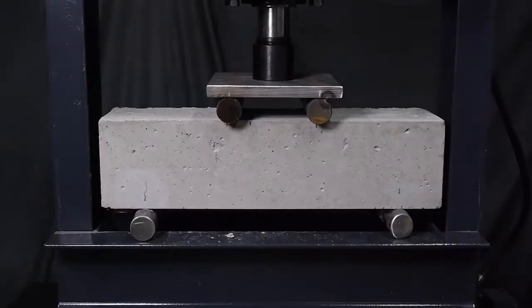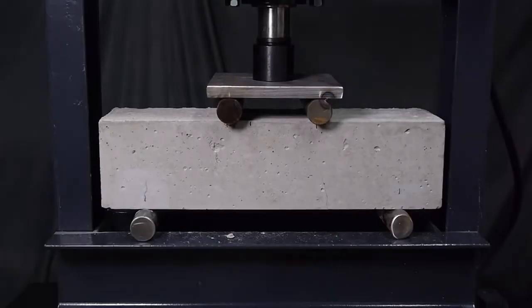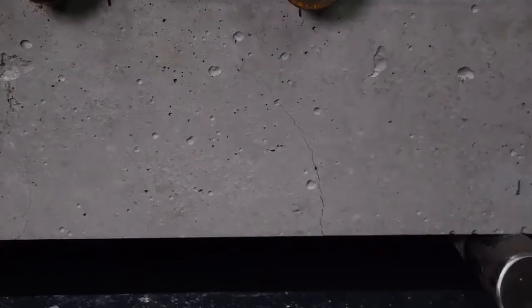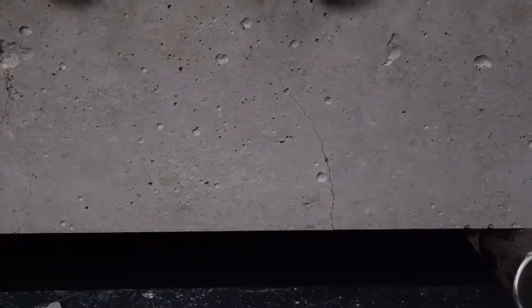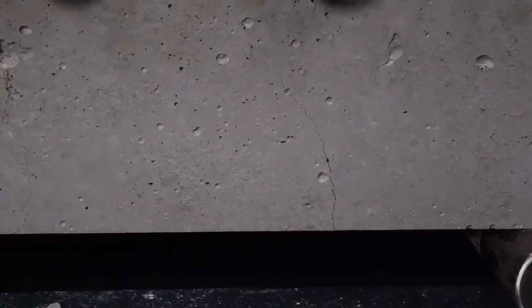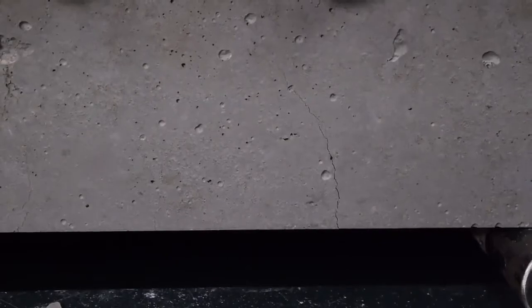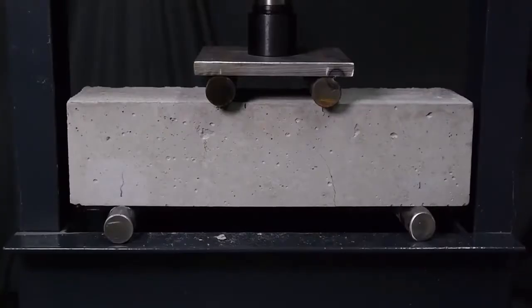As I increase the load on the beam, you see cracks starting at only around 3 tons. These cracks form because steel stretches a little bit as it takes up tensile stress in the concrete. The beam is holding the load just fine and isn't even close to failure, but concrete can't stretch along with the steel, so it has to crack. You can imagine how these cracks could let water and air into contact with the reinforcement and eventually deteriorate the concrete. Those cracks are the important part of this demo, but I went ahead and increased the load until the beam failed, because hey, that's what hydraulic presses are good for, right?